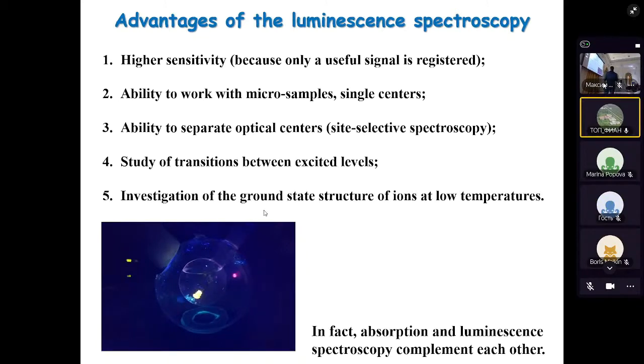Also, we have the ability to separate optical centers, so-called site-selective spectroscopy, using different excitation wavelengths or, for example, X-rays. Also, we can investigate the transitions between excited levels and investigate the fine structure of the ground state of ions, for example, rare earth ions at low temperatures. But in fact, absorption and luminescence spectroscopy complement each other. So it's really good to use these two techniques for understanding some material properties.